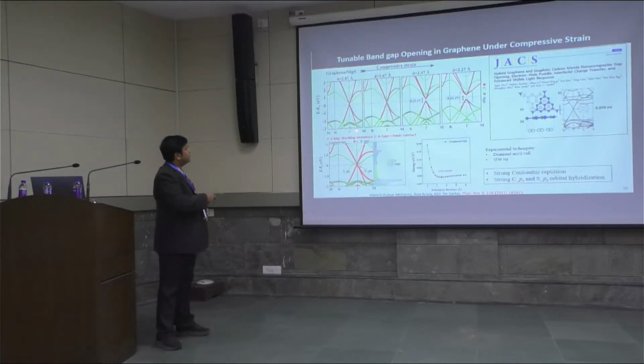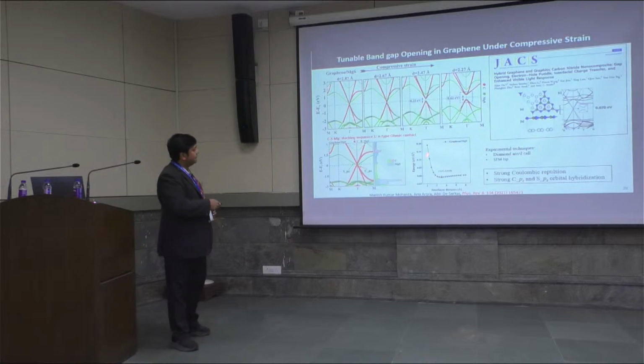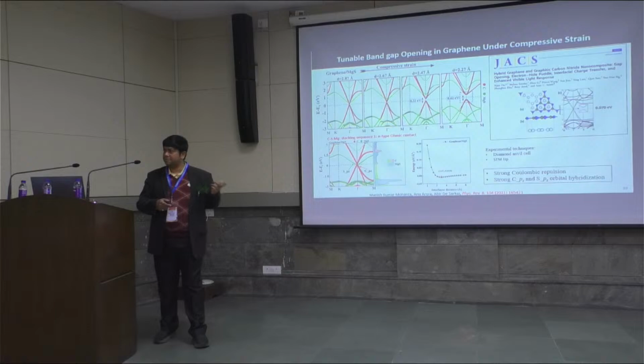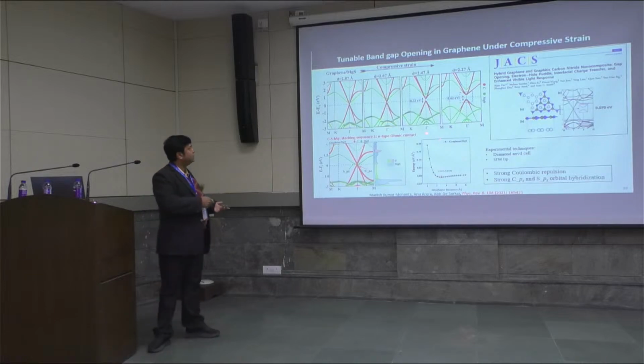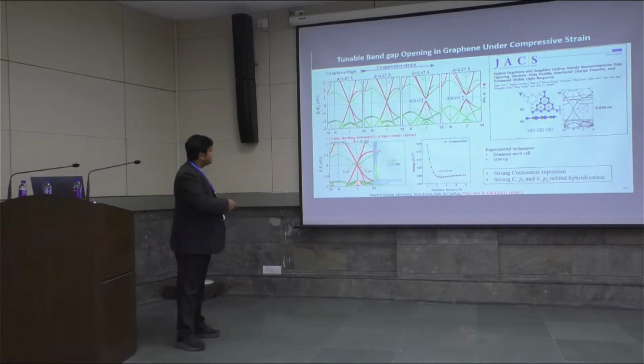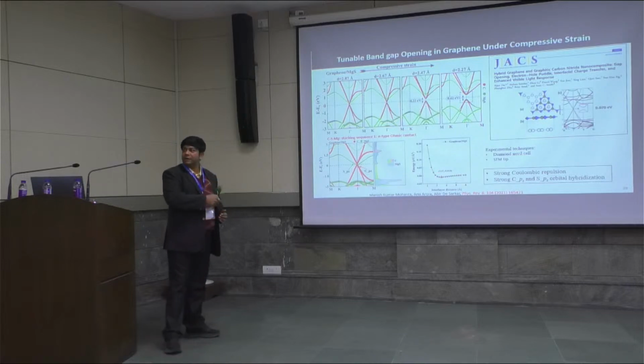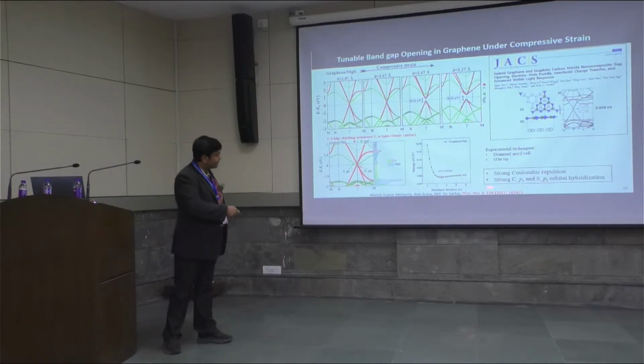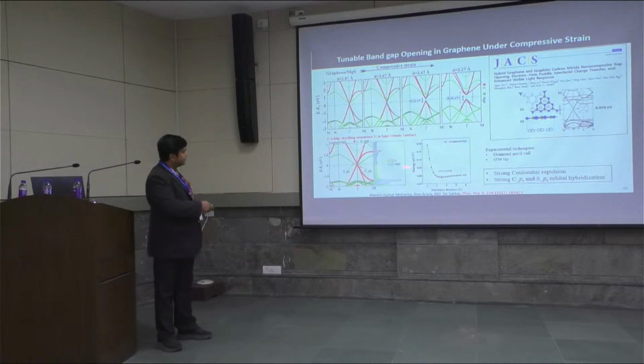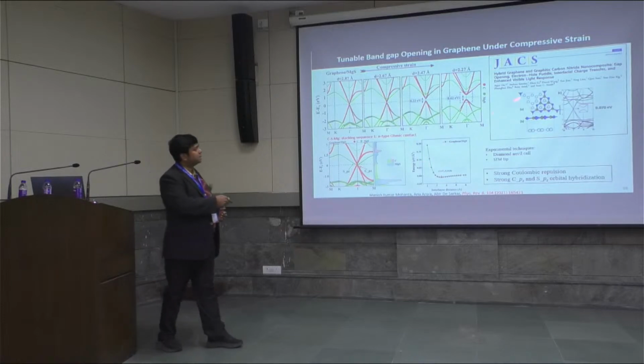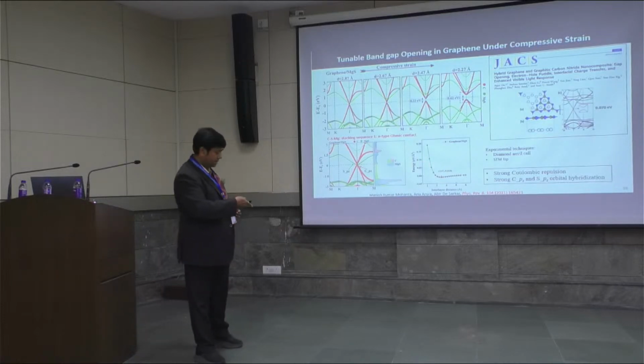And then we have also opened the band gap in graphene by the application of vertical compressive strain. This has relevance to Professor Pandey's talk in the morning. When the two layers are brought closer to one another, there is a strong hybridization of the sp2 and pz orbitals. And when you go past the equilibrium distance of separation, there's a strong Coulomb repulsion. A cumulative effect of these two factors facilitates the opening of the band gap. The band gap which is opened is much higher than the ones reported earlier.